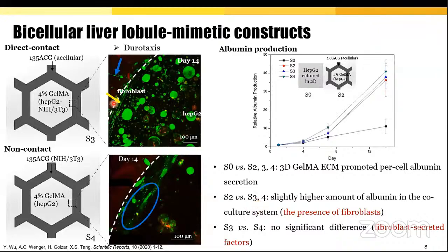Bicellular 3D constructs with direct contact and non-contact interaction between HepG2 and the supporting fibroblast cells were fabricated to study the effect of the co-culturing. In the direct contact system, fibroblasts and the HepG2 cells were mixed in GelMA filling the middle cavities. HepG2 cell spheroids were formed and the fibroblasts elongated and spread over time. Interestingly, fibroblasts protrude from the soft GelMA matrix to the stiff 135 ACG hydrogels due to the durotaxis, and they align parallel along the boundary between the two different materials.